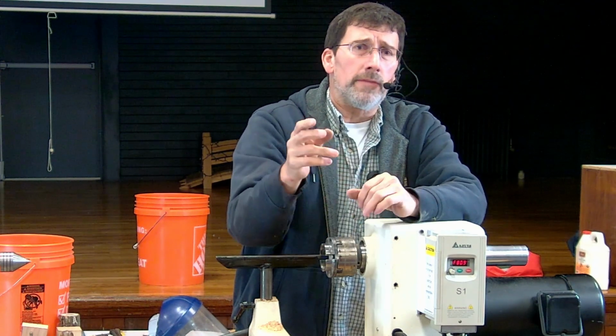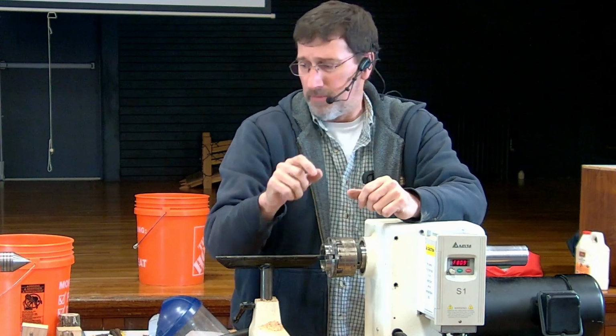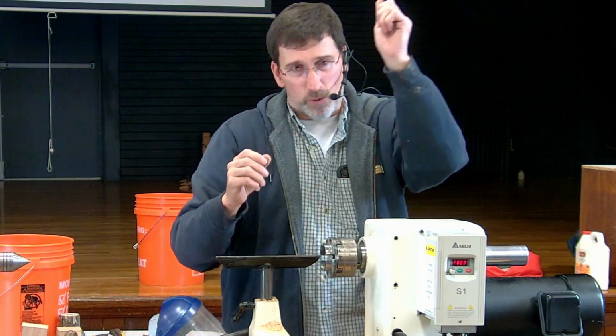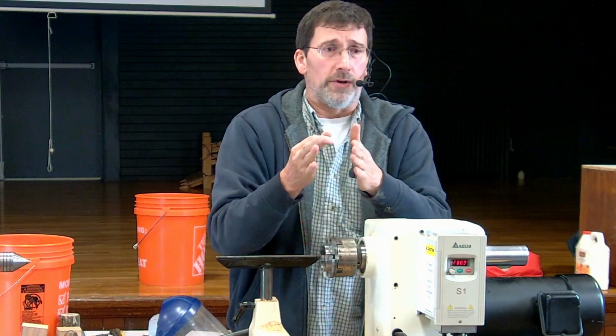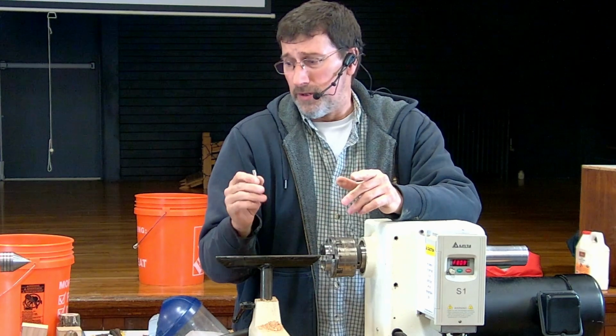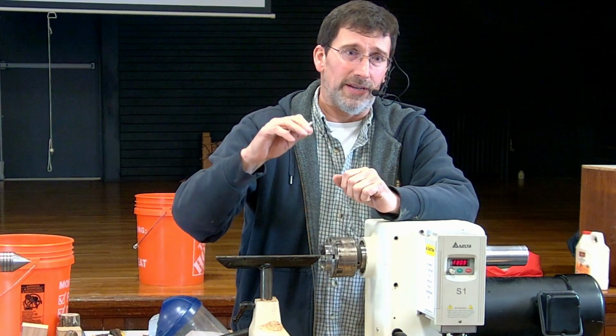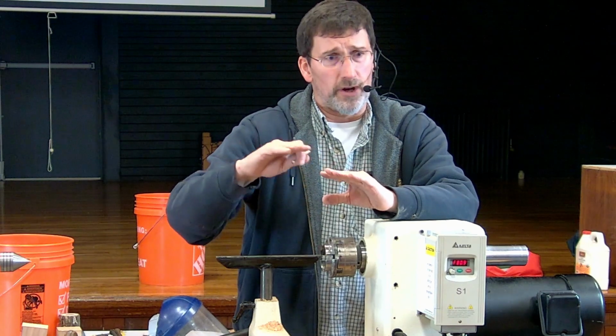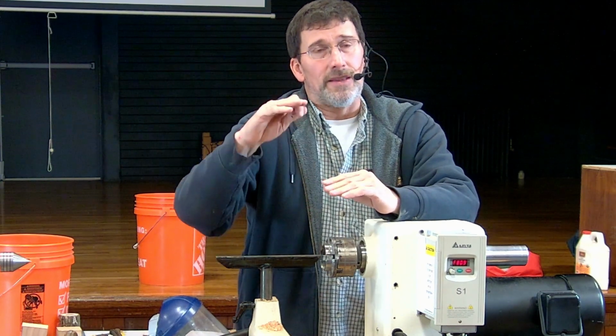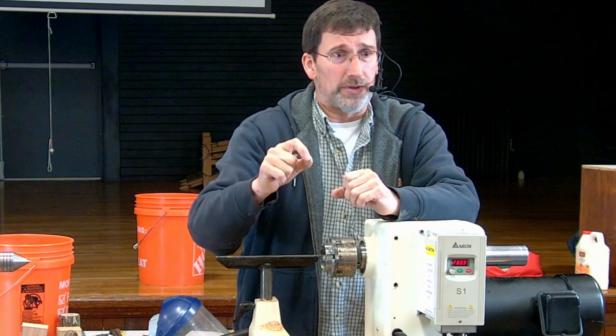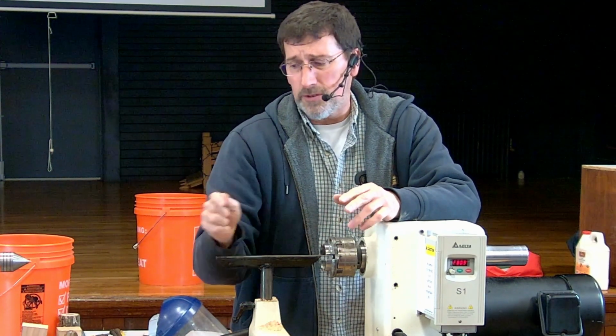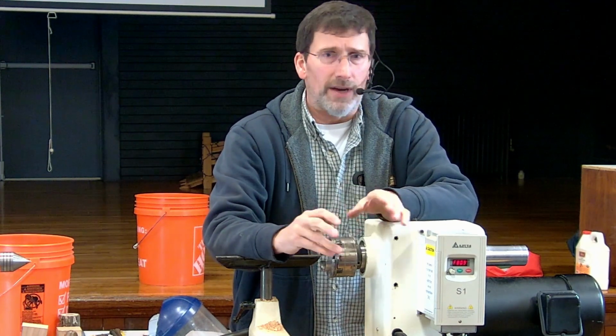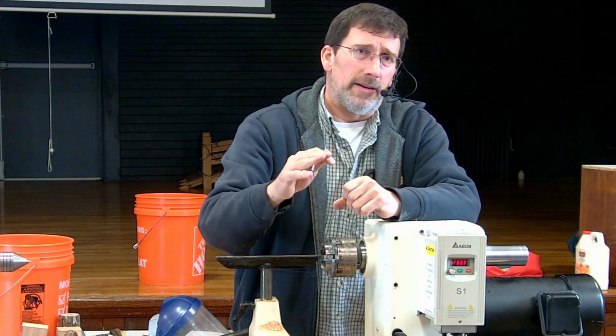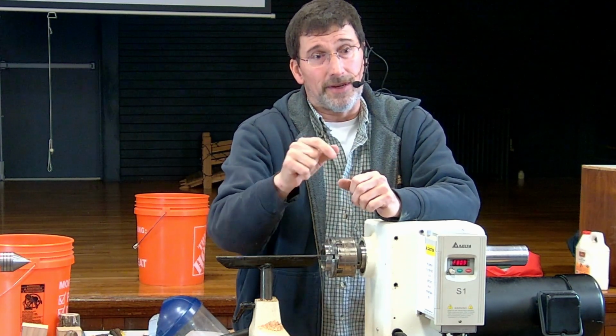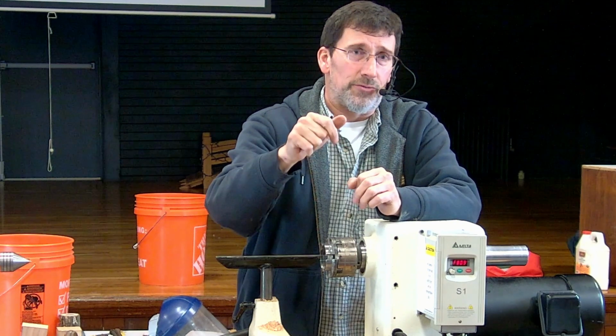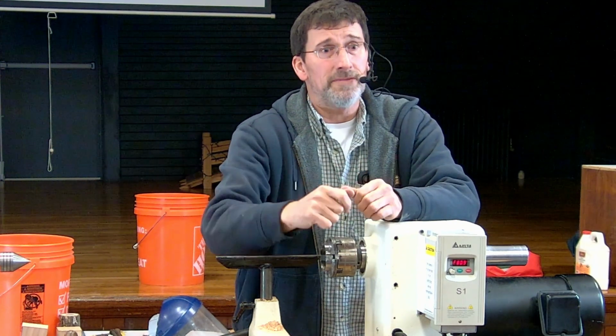At that point, you're better off getting it up until it's non-magnetic, quench it, and that will put the hardness back into it. And then carefully heat it to a straw or like a yellow color, and that'll take some of the brittleness out. You can also not do the tempering, depending on how much of the tip you heat it up, but you just have to understand that you're trading hardness for brittleness.